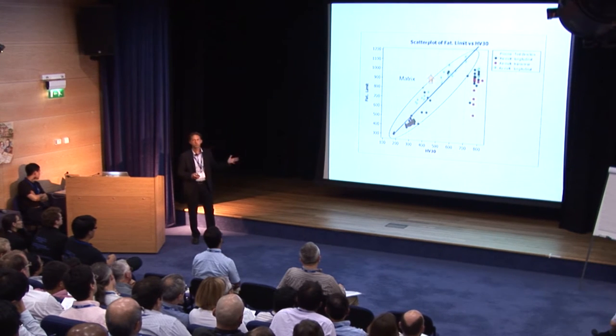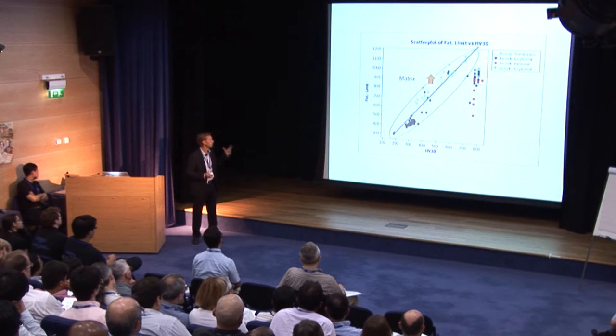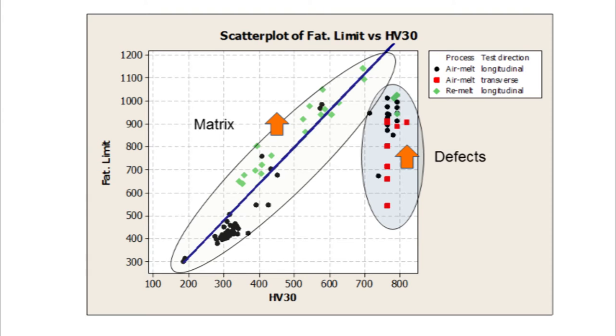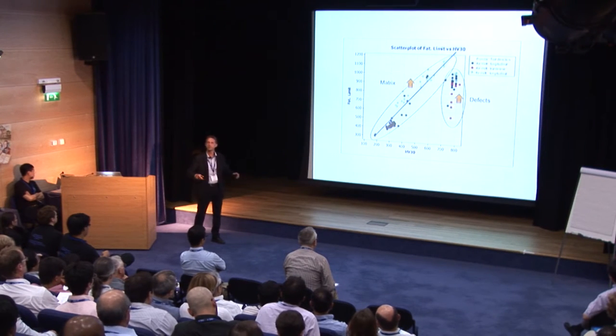So, of course, the reason is, as you all know, the matrix will control this part, whilst the defects will control this part. And the challenge is really, how do we move up above this line here, which is a typical thing that you would like to challenge this nanobainitic material and have more tests about them, because what we're seeing is that it is possible to go over this empirical, theoretical, simplified model. It is possible. I think that's something very interesting for the future that we will work with.